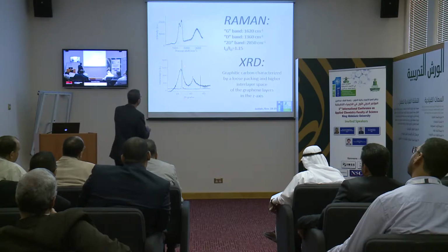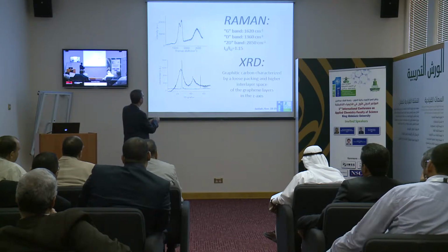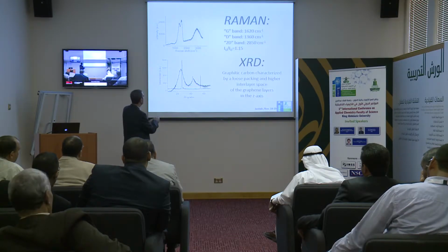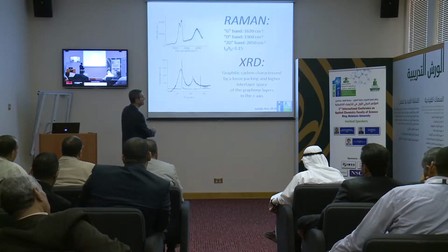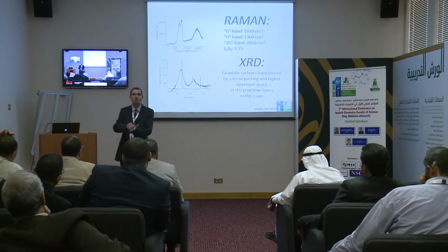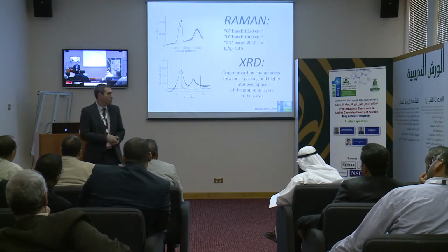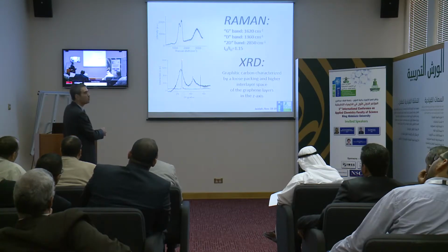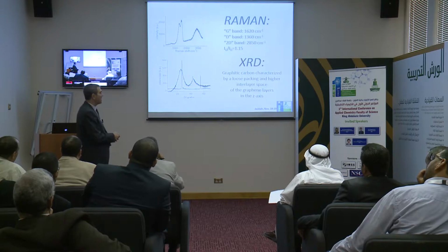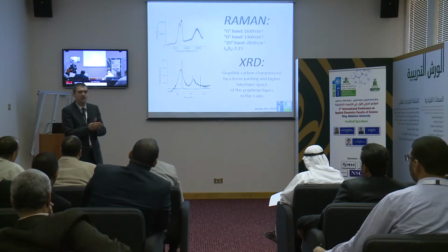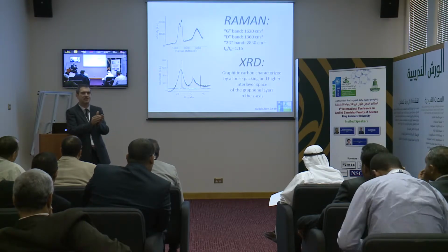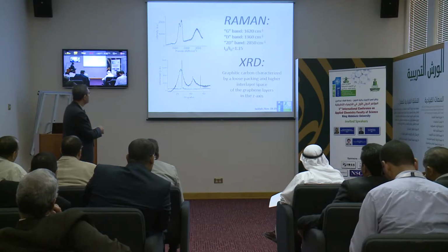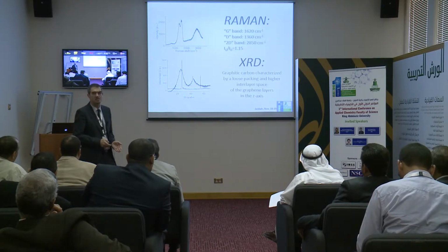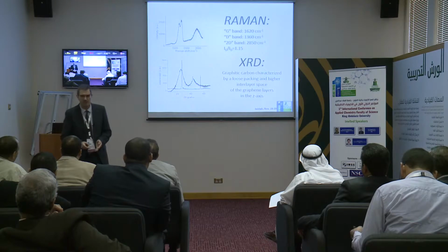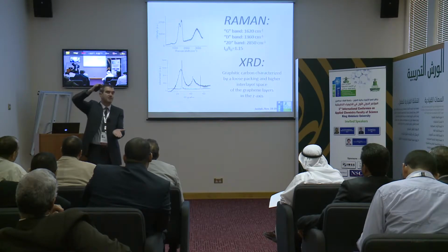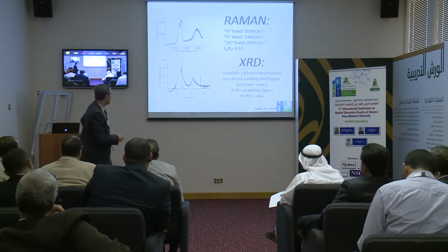And also it's important to notice that there is a shift in this peak from here 25 to here 23 degrees. This shift means that now the layers are more separated. So here the separation between the layers is 0.34 nanometers, and for this reason it's very difficult to exfoliate because the interaction between the layers is very, very strong. But this shift means that now the separation in the layers is 0.5, 0.6 nanometers. So this means that they are further separated, so now it's much easier to exfoliate.